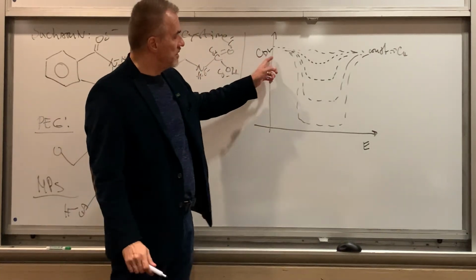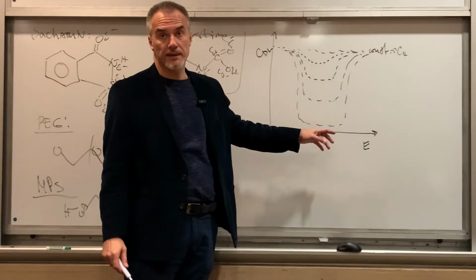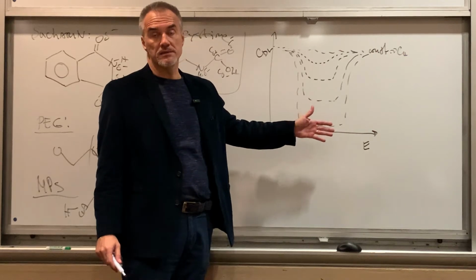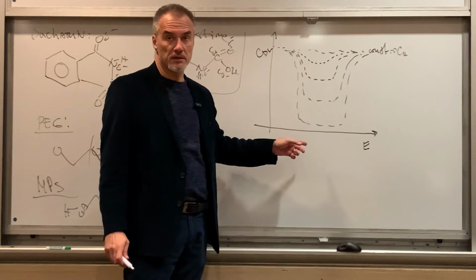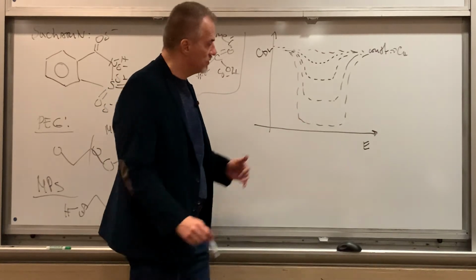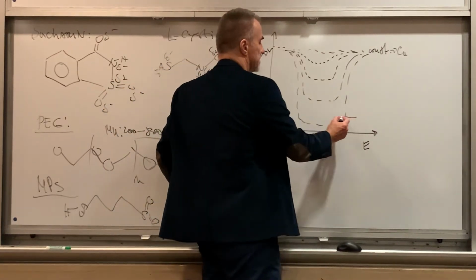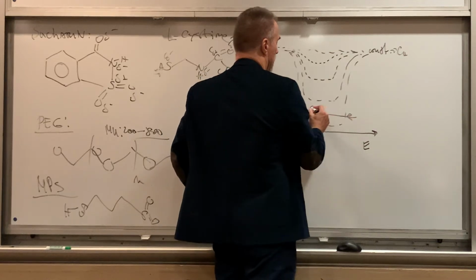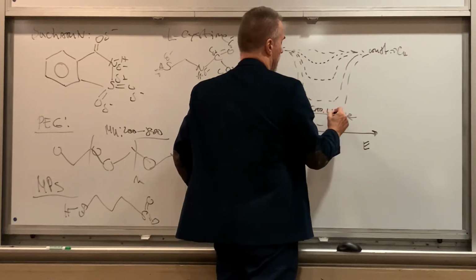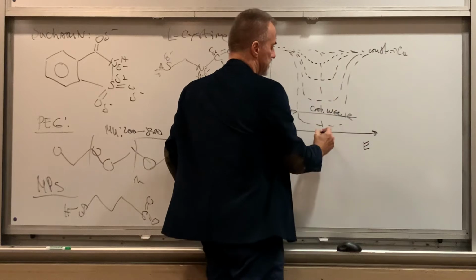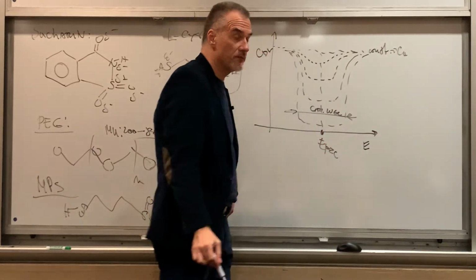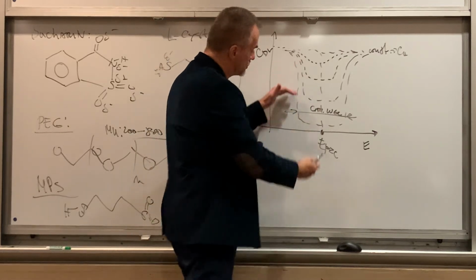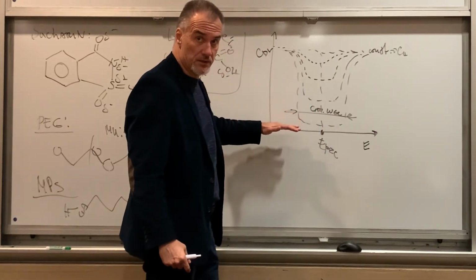So the capacitive double layer will start showing its dependence on the presence of this chemical in the solution, and then more likely you will see that this capacitance minimum will be around PZC, and it's going to show a decrease.